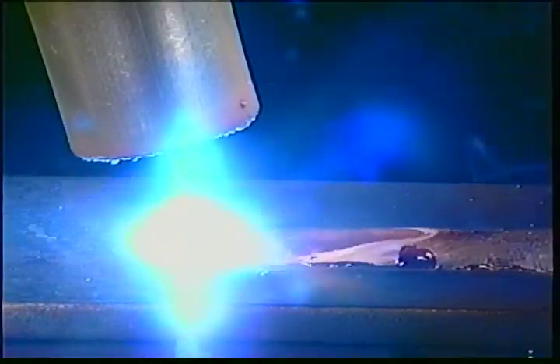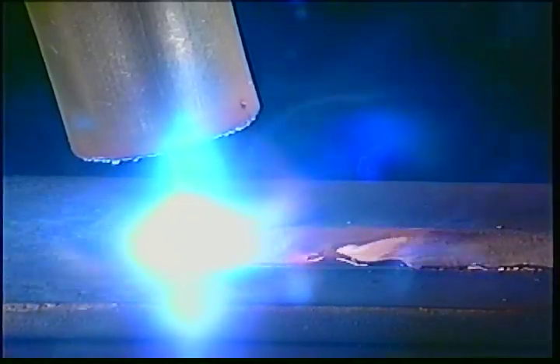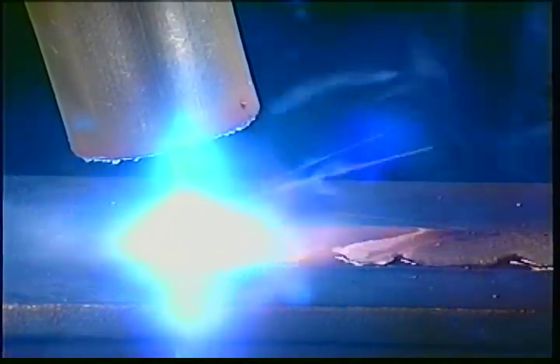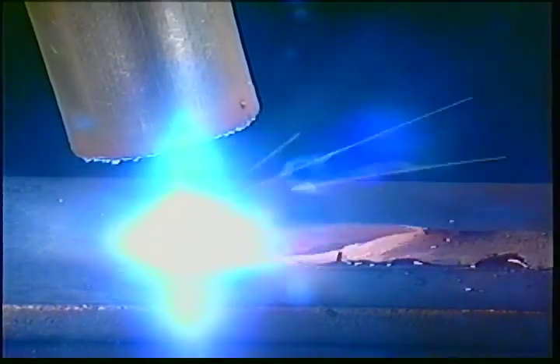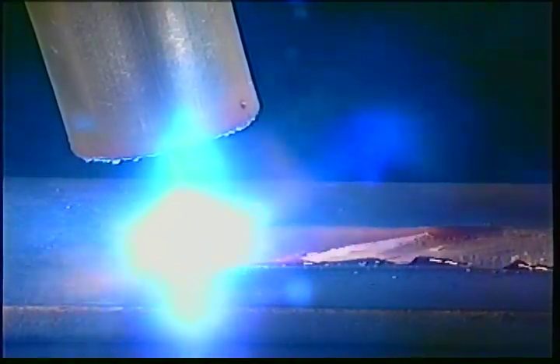By doing this, we get the high deposition of the spray process and the cooling of the weld pool and out-of-position capabilities like those found in short-circuiting. Pulsed spray combines many of the advantages of short-circuiting and spray transfer. Among them, the ability to use spray transfer on thinner material. An experienced welder will have success welding out of position and on materials as thin as 18 gauge, and there is little or no spatter.